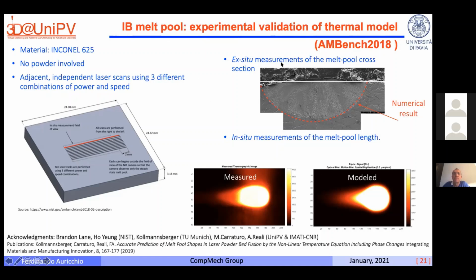And here I'm showing you some very interesting results compared against experimental results produced during the additive manufacturing benchmark in 2018. For example, you can see here some ex situ measurements of the melt pool cross section. There were some runs of your laser, and then the component was taken and cut, and you can see the numerical result with the red curve and also the experimental data. You can see that there are some differences, but there is a very good match between the prediction and the experiments. You can also see some in situ measurements of the melt pool length. Here you can see on the left the measured melt pool, on the right the model melt pool, and there is a good match between prediction and experiments.